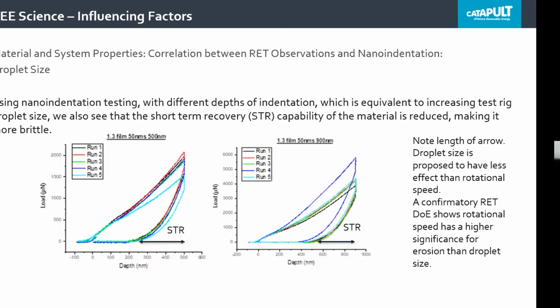We've confirmed these very recently against rain erosion tests in a DOE, and it shows basically that the rotational speed has the highest significance for erosion, and that's great. The second next order is the droplet size. So therefore, we feel that nano indentation, if you can measure it on your material, could be a good indicator test, perhaps, of its erosion performance before it goes into the rain erosion test rig.